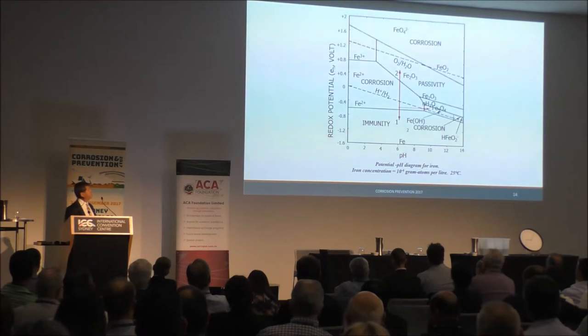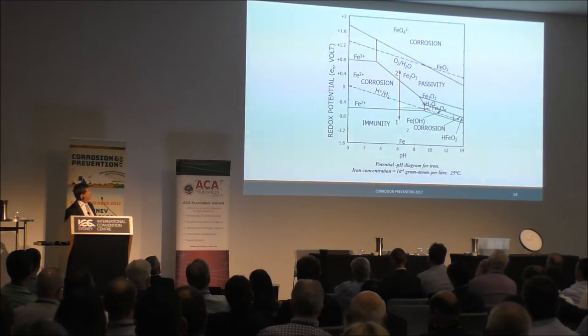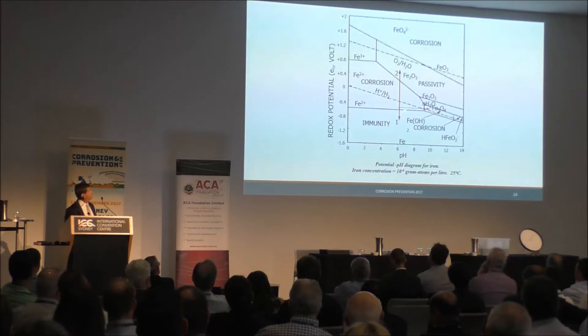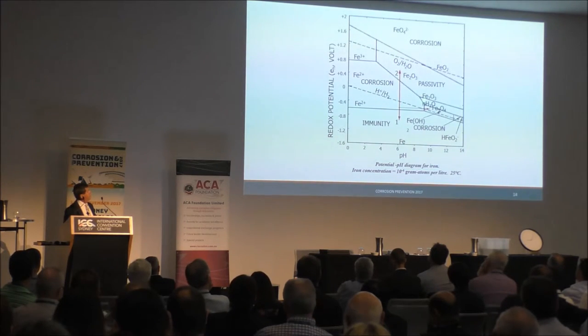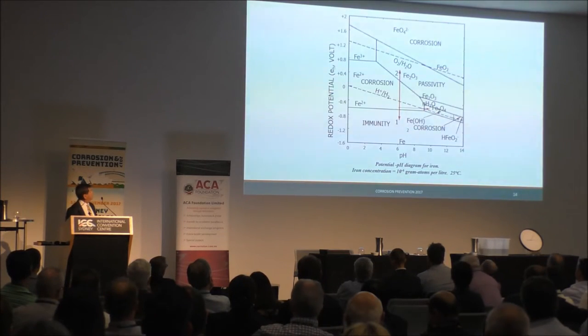So in deoxygenated water, how do we stop the corrosion? You have three options. One, you can forcibly reduce the electro-potential of the metal into this region of immunity. How do we do that? Well, we could put a piece of zinc and attach that to the iron to force the iron corrosion redox potential to become immune from corrosion. Or we could add oxidizing agents and force that electro-potential high enough up until the sample reaches this passive region. Or we could increase the pH to get at least a reasonable passivity for the iron under these conditions.